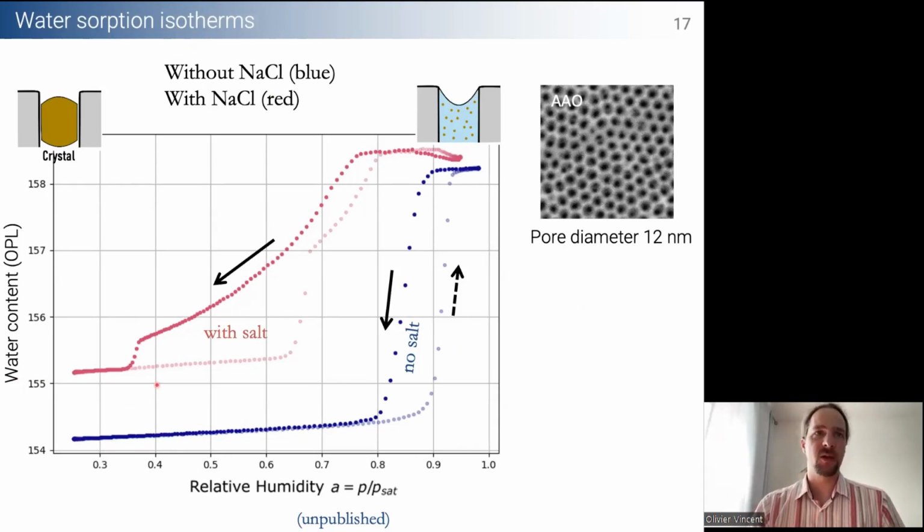And we cycle the humidity between very low, let's say 20 to 30%, and very high humidities close to 100%. And this is well known: if you have a nanoporous medium and you cycle humidity above it, when it's at low relative humidity, the medium is basically dry with potentially some adsorbed molecules on the pore walls, but not bulk liquid in it. If you increase the relative humidity by going to the right here, at some point you will get capillary condensation that I talked about before, and that drives capillary imbibition in some cases.